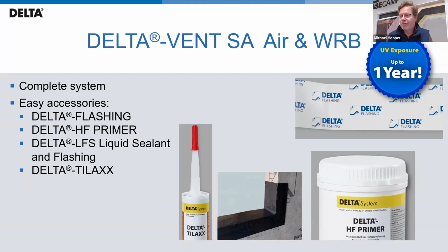You have a really good high quality adhesive and it sticks to whatever you stick it to. If you stick it to dirt, you got a really great bond to that dirt, not to the substrate below it. When you use a primer, you encapsulate that dirt with adhesive and basically glue it to the substrate. And then when you put your air barrier over top, you are in fact adhering to a glue that's adhered to the substrate. Yeah, I can't tell you how many projects I have witnessed that the primer was the main culprit of it not working, either being rushed or put on too thick or not put on at all or too much time in between. But primer is really the key to a lot of these components. It's a part of your system, and it's nice to have options.